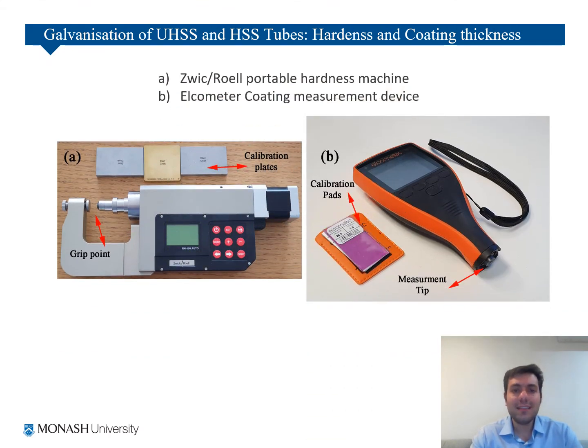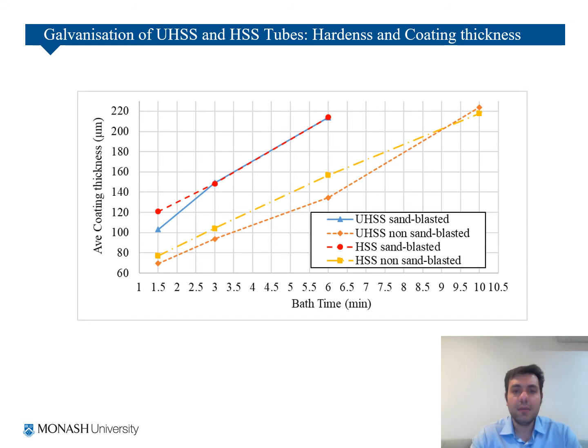Then we conducted some hardness tests, and we measured the coating thickness using this device. These are the coating measurements, and we made a lot of measurements, and we averaged these. So you can see here that by increasing the bath time, the coating thickness is increasing, and by sandblasting, the coating is shifting up, so the thickness is increasing in all bath times. So actually sandblasting was not a good option, and also it's better to keep the dipping time around 1.5 to 3 minutes to gain a good coating which is not thick and is not brittle.